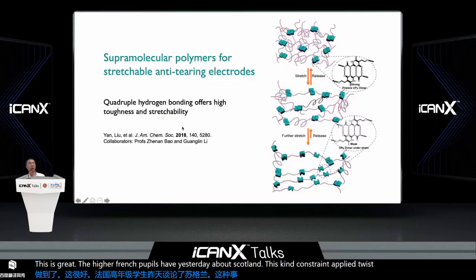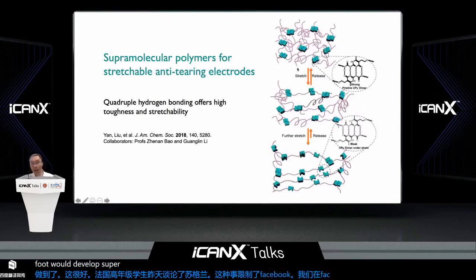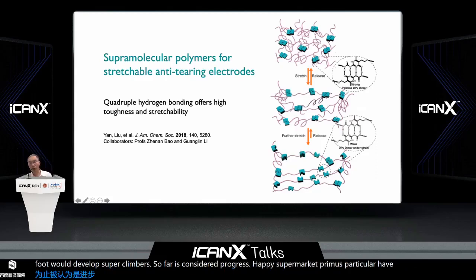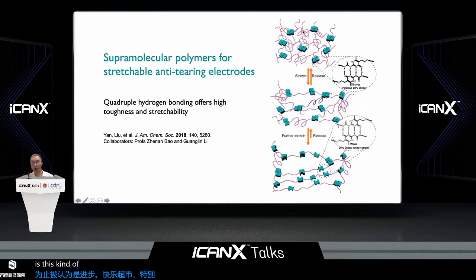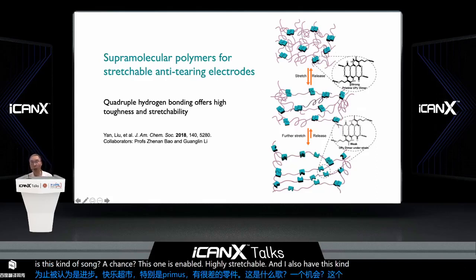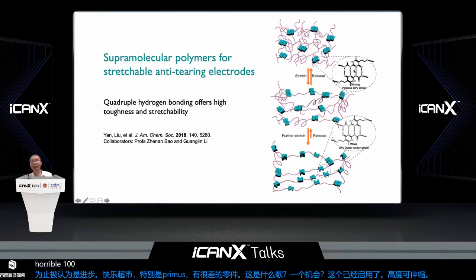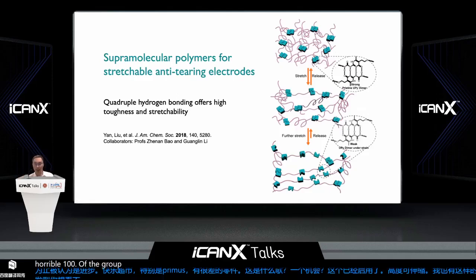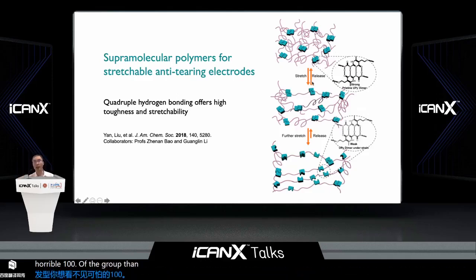Two years ago, we worked with Zhenan's group. Her group developed supramolecular polymers. These supramolecular polymers particularly have two components. One is soft polymer chains, which enable high stretchability. The other is hydrogen bonding. This hydrogen bond is reversible, and it offers high toughness. Because these two come together, these supramolecular polymers have huge stretchability and also strong healing capability. The stretchability can almost go to 170 times compared with the original size.